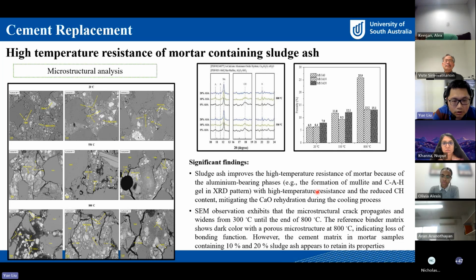But this calcium oxide will possibly rehydrate during the cooling process. Then with a 44% volume expansion, that expansion will damage the concrete significantly. If we consume more calcium hydroxide, then we can mitigate such damage.